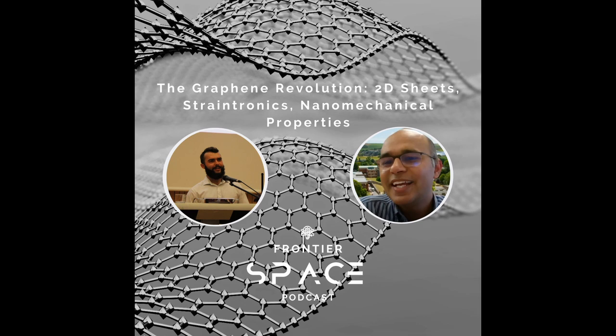The second problem that the industry is facing is that it is difficult to control the strain. Strain is the change in length over the original length. It means that when you stretch the material, the length changes. So it is difficult to control this. For example, at 0.2% strain you are getting a different material, and then you have to maintain this strain throughout the material. Otherwise, if some region gets 0.3 or 0.5 strain, the material will be more semiconductive because the band gap changes. So that is a difficult part. In the laboratory, we have tiny chips, about 1 centimeter square. But in industry, it will be massive. So holding the strain or stress distribution along the 2D material is not that easy.